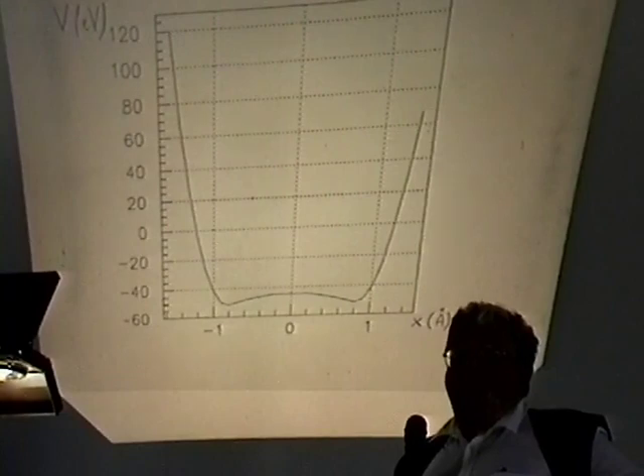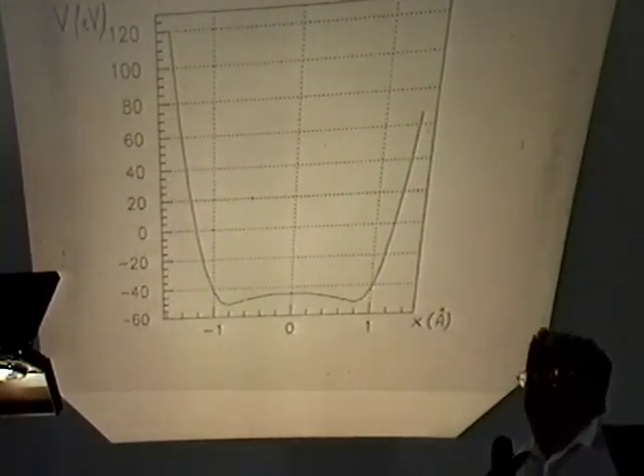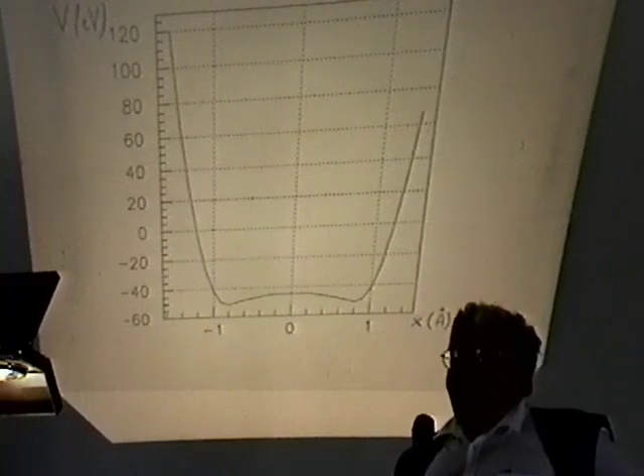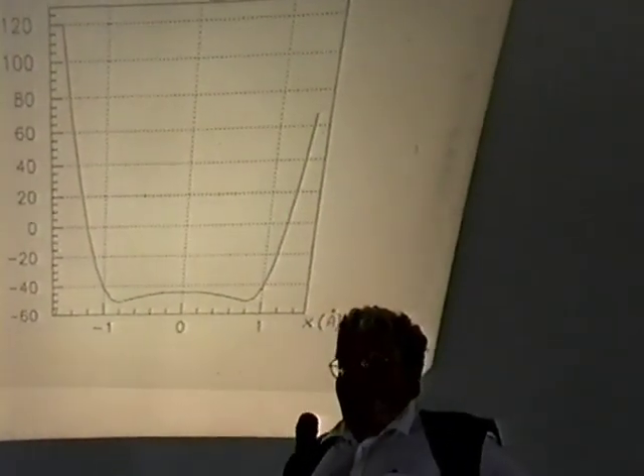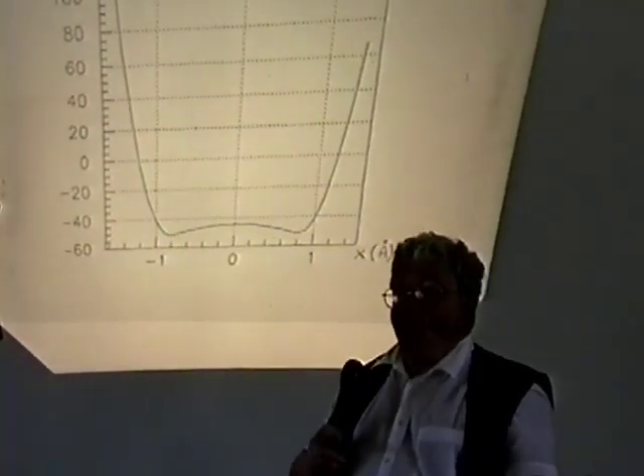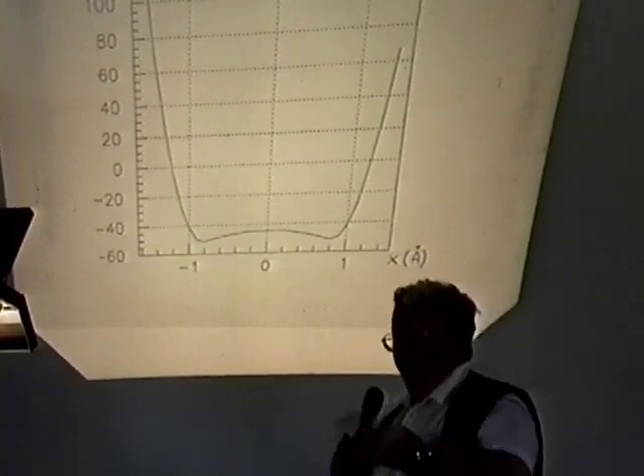But the existence of such a well is necessary in order to understand, as Alfred Coehn has discovered, why hydrogen gets ionized when entering into the lattice. So the existence of such wells should be accepted necessarily, otherwise Alfred would have been wrong. In the tetrahedral sites, we have this different kind of wells, much narrower and deeper. So compare the two kinds of wells. In the octahedral site, the potential is like that, and in the tetrahedral site, like that.